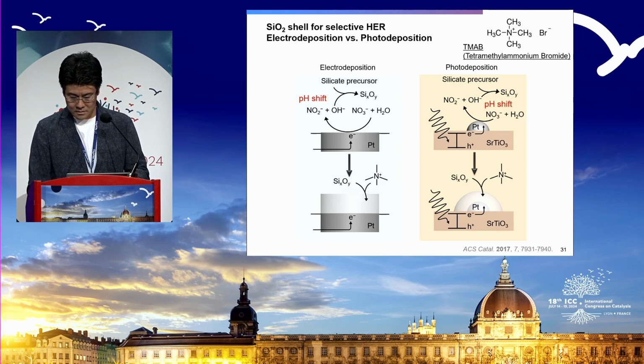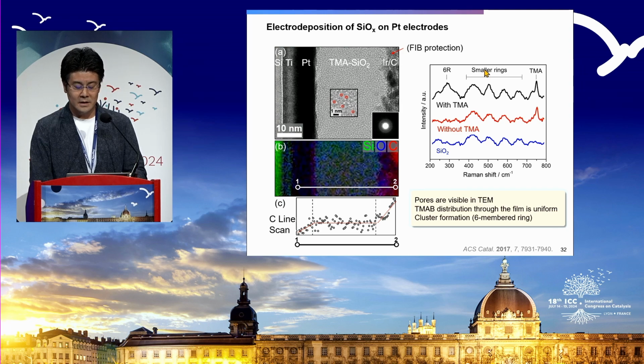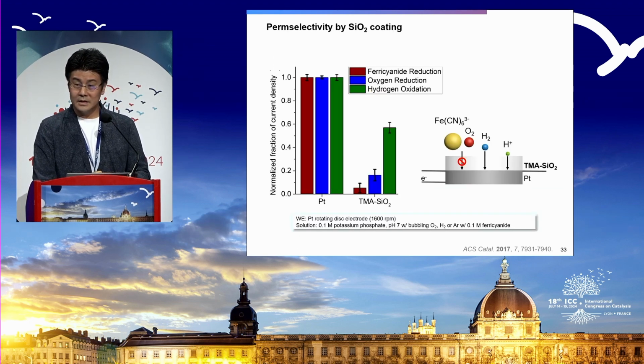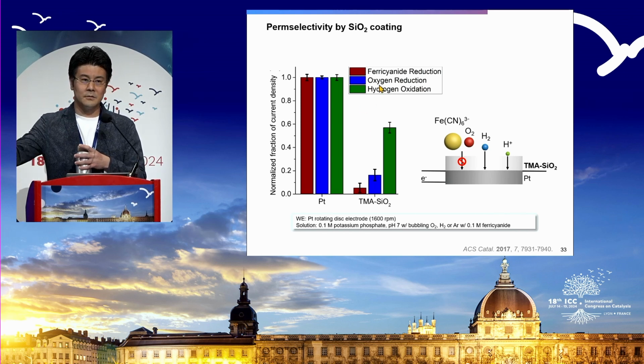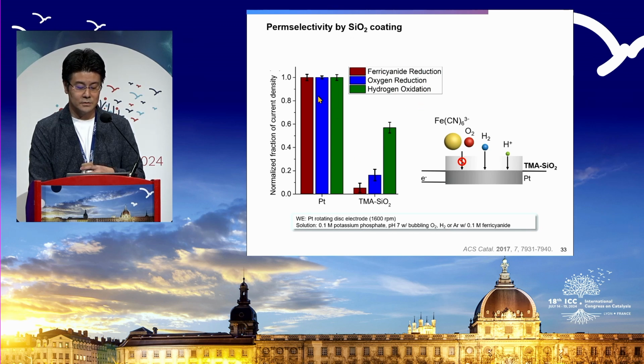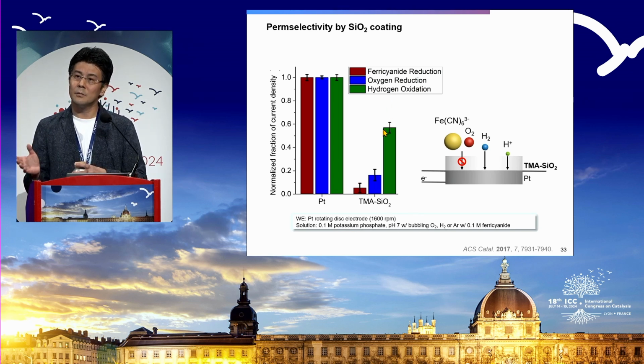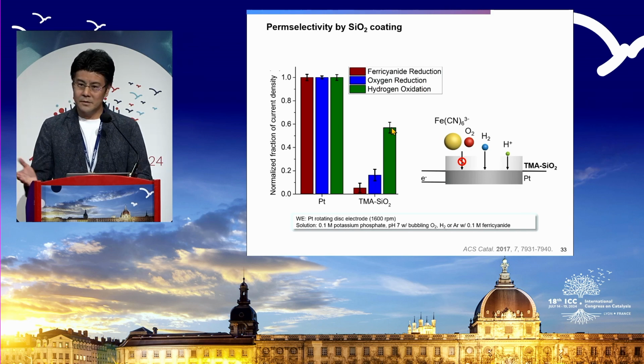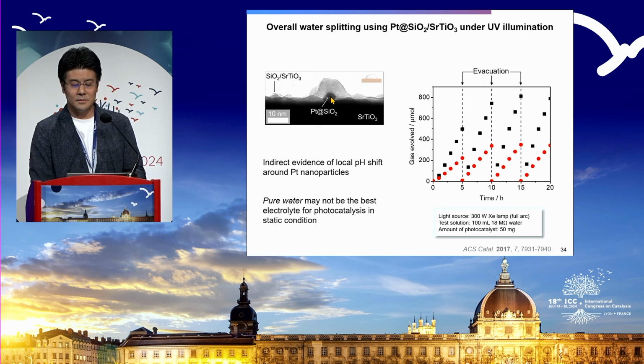So then what we need to show, okay, first, electrodeposited silica with tetramethylammonium as a structure-directing agent. We see this 6-member ring accumulated, and that actually makes a nanomembrane on this platinum electrode. And we can see the selectivity, so the large ion cannot penetrate through this silica. You can see the ferricyanide reduction is not occurring, relative to the bare one. You can completely suppress this iron reduction. But the hydrogen, the smaller molecule, can penetrate through. So there is a membrane function on this silica. And in fact, this is covered selectively on the platinum. So you can see that the pH shift is actually occurring, so that you can deposit silica close to the platinum electrode, the platinum nanoparticle co-catalyst.